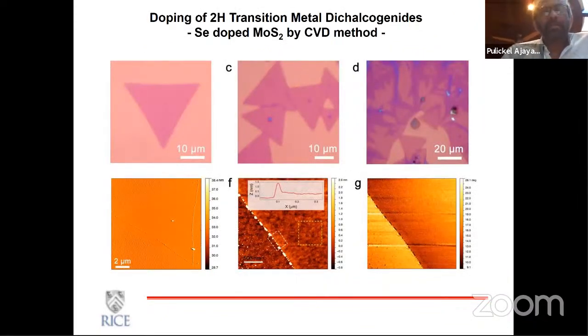And the final thing is, again, going from two components to increasing the number of components, going to ternary systems or tertiary systems, and seeing how they mix in chalcogenide systems. Again, as I said, lots of work has been done on these kinds of materials like molybdenum sulfide in catalysis and many practical applications. But atomically speaking, very little is understood. For example, when you dope them. In fact, doping is actually a technique to increase catalytic activity, and this has been practiced by people who are working in these areas, but never really correlated with how exactly the structure changes as you do doping.